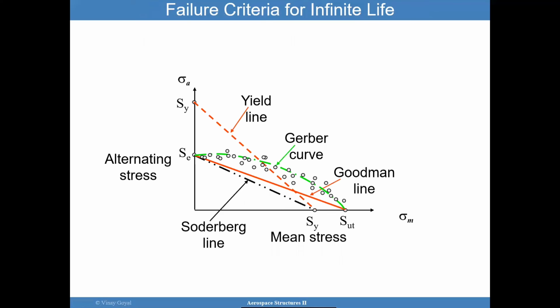So there are a lot of different failure criteria to demonstrate infinite life. One is, for example, the yield line. You have the Goodman line. You have the Soderberg line, which connects Se and Sy instead of Se and Sut. That's a little more conservative. You also have the Gerber line, which does a fairly good job. So again, these lines are intended to give you a prediction of when you get infinite life. And if you stay in this zone here, you're fairly safe. But it is fairly tough to come up with the right one for every situation.